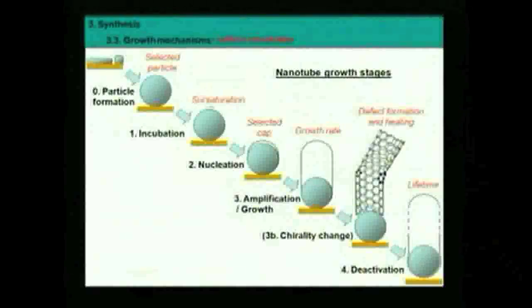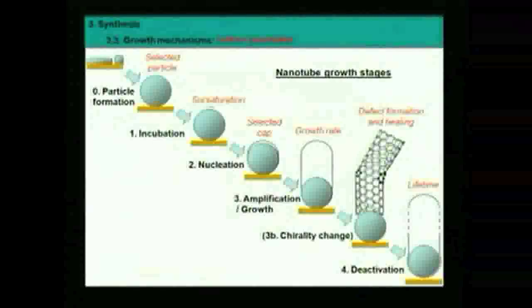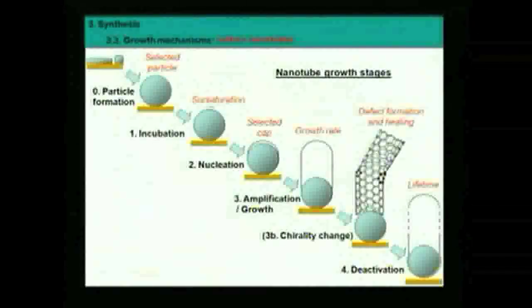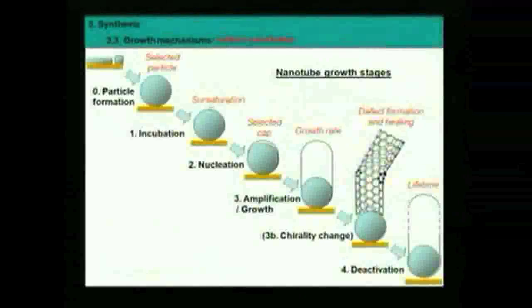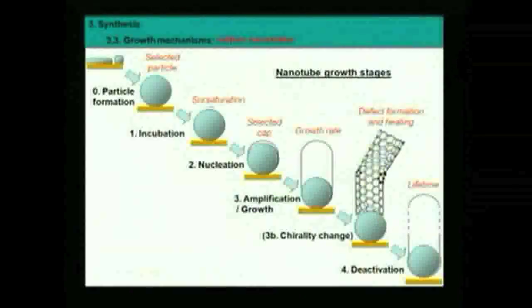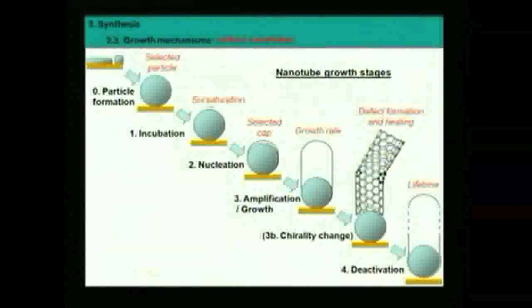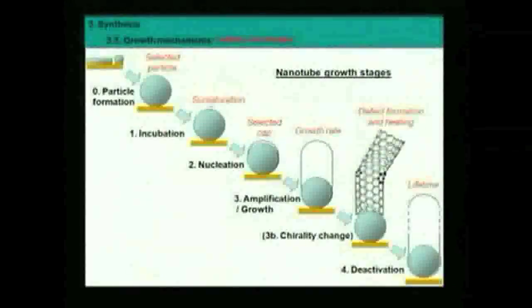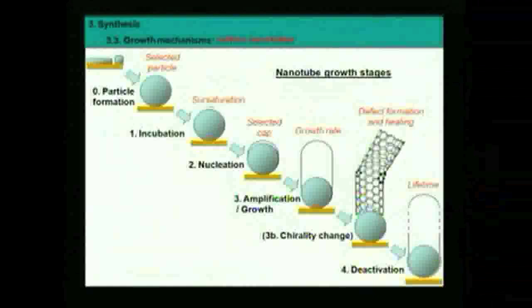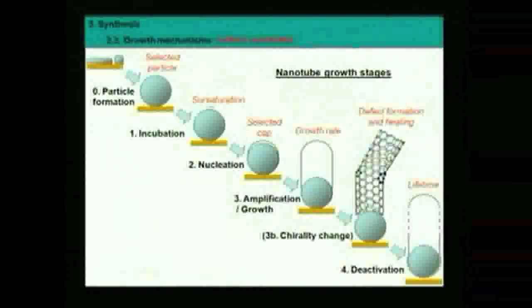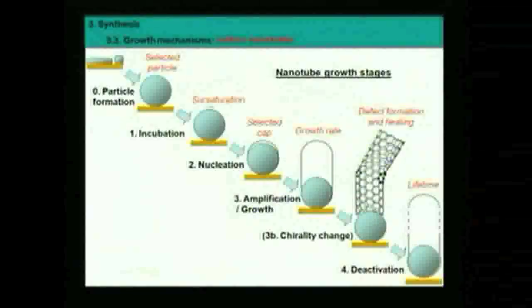Then this cap will cover the particle. There is a template effect. We have seen this template effect. The cap reproduces the shape of the particle. This is really important. And then we got addition of more carbon atoms to amplify this seed. What we haven't seen, but we observe sometimes, is that there are defects included in the nice graphene lattice, like heptagons, pentagons. And then what we are going to see is that the growth stops by itself. The growth is not infinite. It will stop by itself after some time. And there are many reasons for that, and we are going to look at them later.